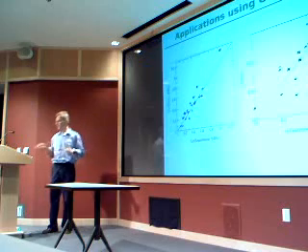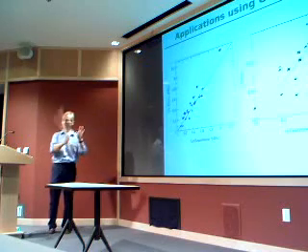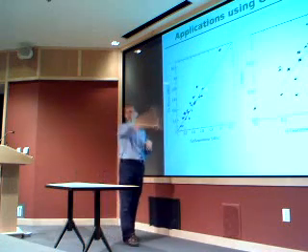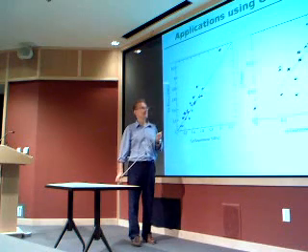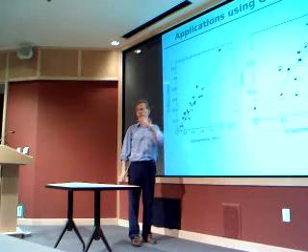What is this eta? This was the anisotropy. If you remember, the 2 eigenvalues, you have Vxx minus Vyy divided by Vzz, etc. So it goes from 0 to 1, the range can be in theory. Why is the scatter, the spread, so high in the case of anisotropy? Well, maybe it's more sensitive for small numbers because you now take the difference of the 2 eigenvalues.